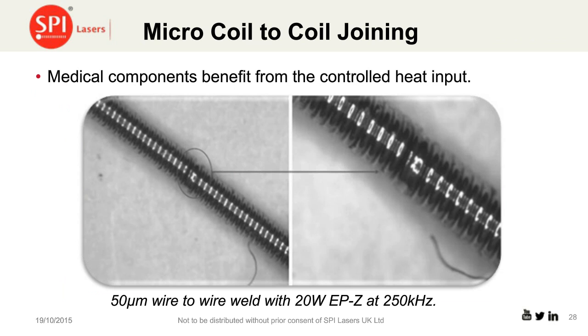We have been doing this for a number of years in terms of using these lasers for generating small parts. Coil joining, wire joining, these are applications in industries such as the medical components industry where we need to very much control the heat input. And here is an example of a 50 micron coil where we're welding wire to wire with only a 20 watt pulse laser. And again, the issue here is being able to go to higher frequencies so that we can dull the sharpness of the peak but maintain the focusability and the intensity of the energy to generate a good joint.